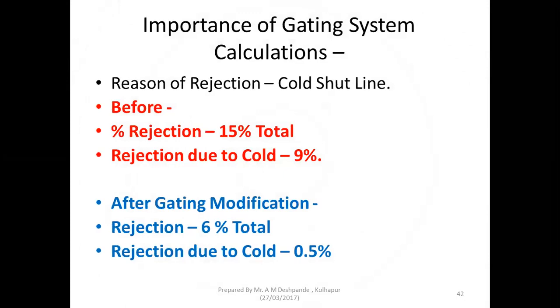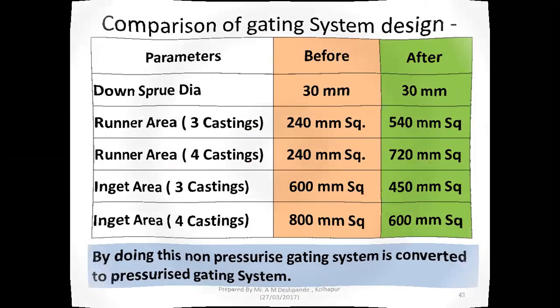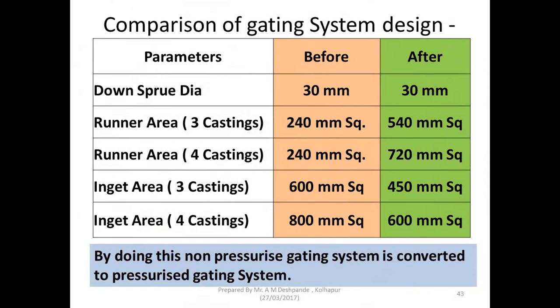Reason of rejection: percentage rejection was 15% total, with rejection due to cold shut 9%. After the modification, total rejection is 6%, with rejection due to cold shut 0.5%. So I request you to see these parameters, before and after. Down sprue diameter 30 mm, 30 mm, I am not changing. Runner area for 3 castings was 240 square millimeters before, and after I made it 540.